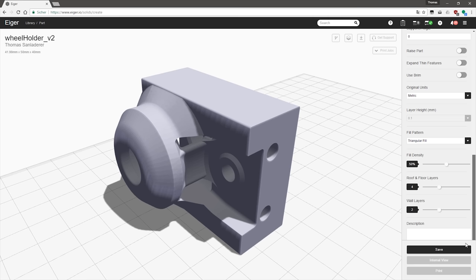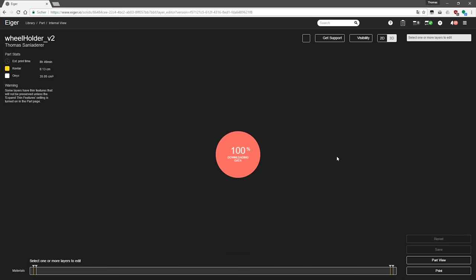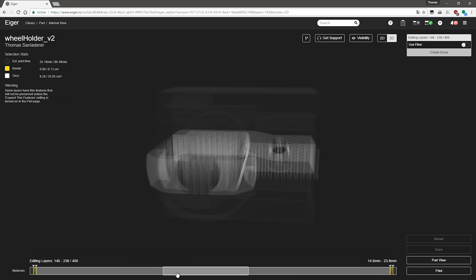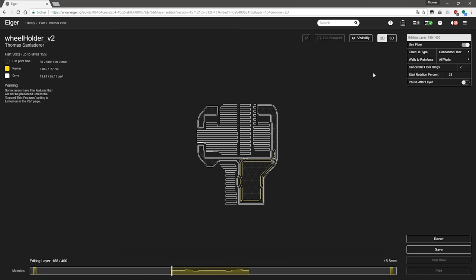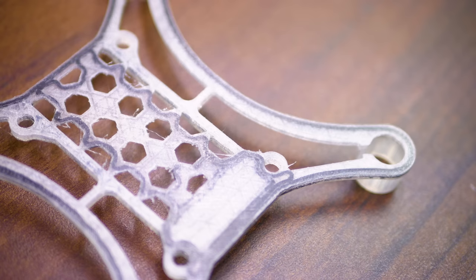Aside from the base material settings, you can of course also decide whether or not and how much continuous fiber to use in the print. Though the fiber algorithms don't feel that sophisticated yet, as they will always try to lay down full loops of fiber throughout the entire layer and only let you control which layers should receive how much fiber and not specifically which areas of the model should be reinforced. The software will always try to encase the continuous fiber in a roughly 1mm thick shell of the base material, since the fiber toolhead doesn't lay down the fibers too precisely.